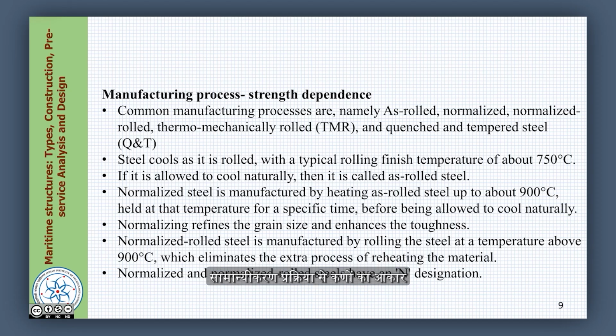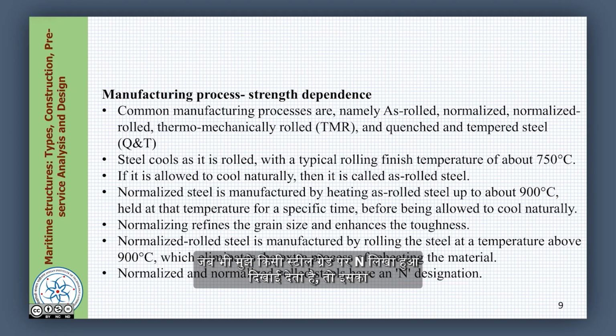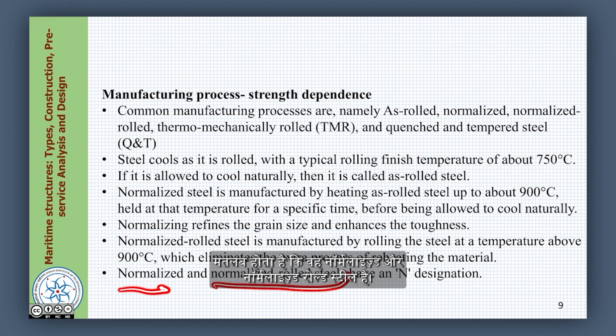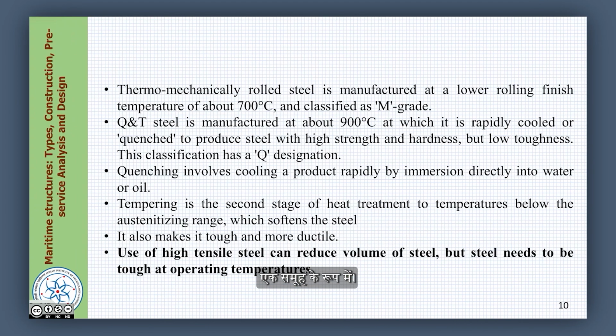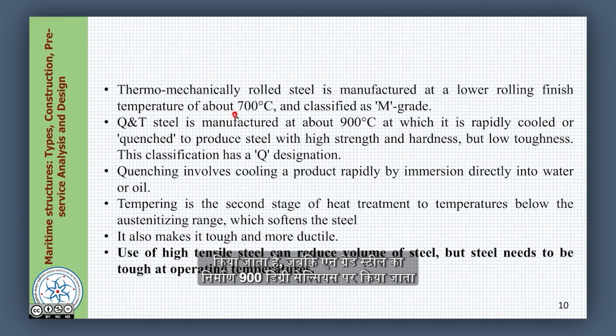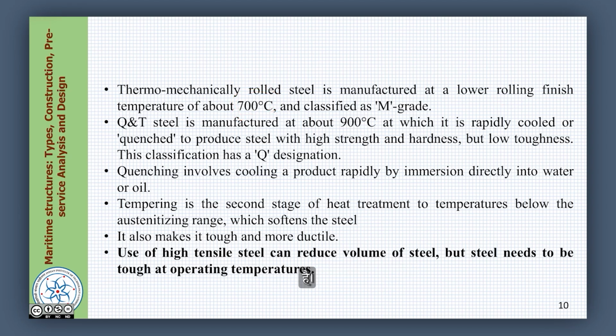The normalizing refines the grain size and increases toughness. Normalized rolled steel is manufactured by rolling the steel at a temperature above 900, which eliminates the extra process of reheating the steel. Therefore, friends, normalized and normalized rolled steels have a designation called N. Whenever you see a steel grade designated with N, it is indicating normalized and normalized rolled steel as a group. Thermomechanically rolled steels, what we call TMR, are manufactured at a lower rolling finish at about 700 degrees Celsius, whereas N grade steels are manufactured at 900 degrees Celsius.